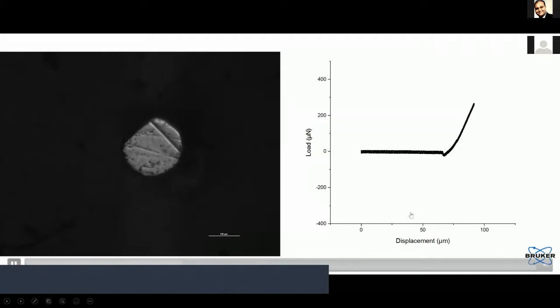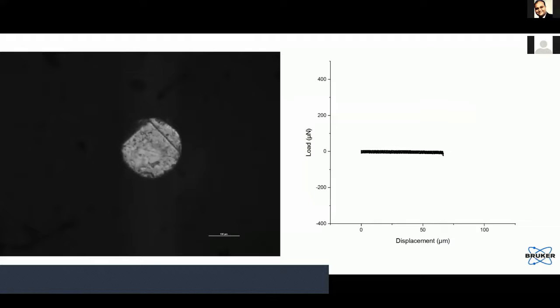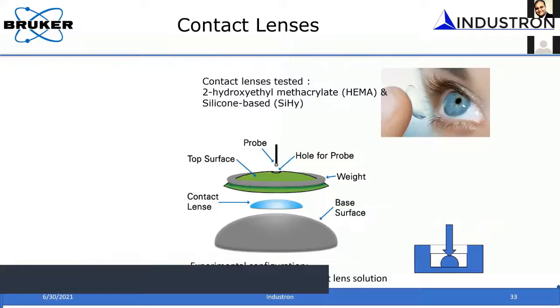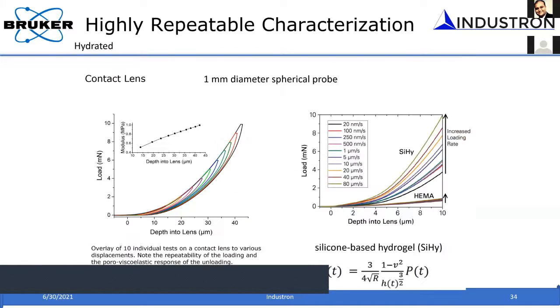So all these things that I was talking about, making a pull-off force measurement, or measuring the stiffness and calculating the property through this load displacement curve, you can still do along with this video image that we can correlate with. That allows us to do experiments on very soft materials like contact lenses. And like I said, if you do it in a liquid environment, you can avoid this adhesion problem. In those cases, these simple load displacement curves you can fit with Hertzian contact mechanics, and you can do that at different rates of loading.